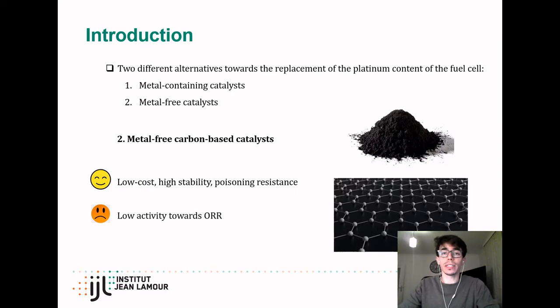All these alternatives can be classified into two different groups. First, the metal-containing catalysts, and the second, and to my mind the most innovative alternative, the use of metal-free catalysts, especially those that are based on carbon materials. Because these kinds of electrodes are low-cost electrodes with high stability and a strong resistance towards poisoning with methanol or carbon monoxide. The main problem of these carbon materials is the low catalytic activity towards the oxygen reduction reaction.